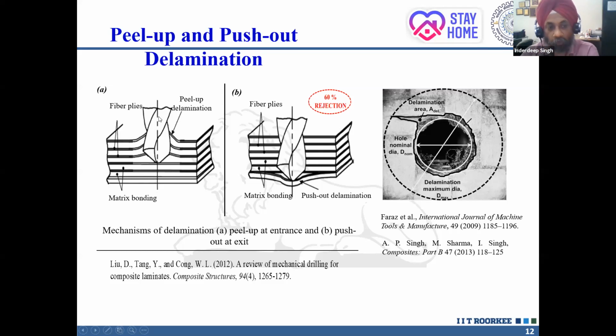These are the layers. Once the drill tends to enter this, the top layers tend to peel up because of the drilling force action. When the drill is trying to enter into the plate, the top layers tend to open up. That is called the peel up type of delamination. Now why is the word delamination coming? Because we have laminated different layers together: one layer, second layer, third layer, fourth layer, fifth layer, sixth layer. So we have stacked up the layers. Suppose we have taken 6 layers and laminated them to make a laminate. Once you try to make a hole, the top layers may tend to open up. That is called the peel up type of delamination.